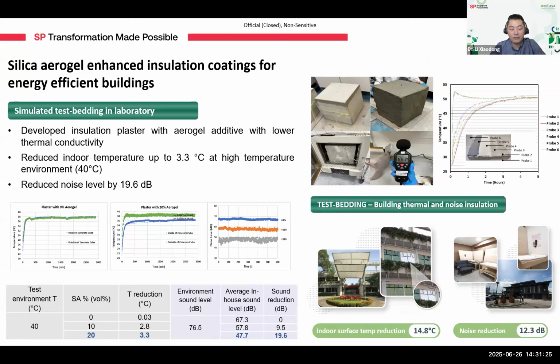And beyond the lab, we have also demonstrated its effectiveness in a real-world setting. At the SP Graduate Guild building, we recorded a surface temperature reduction of up to 15 degrees Celsius after applying our aerogel-based coating. Please note this refers to the surface of the coating, not the indoor air temperature, but it clearly illustrates the material's heat-blocking capabilities.